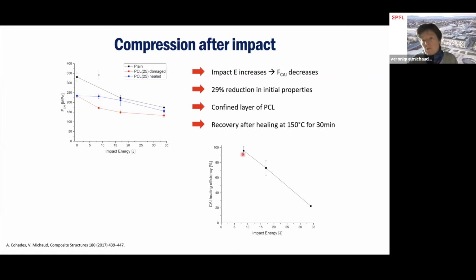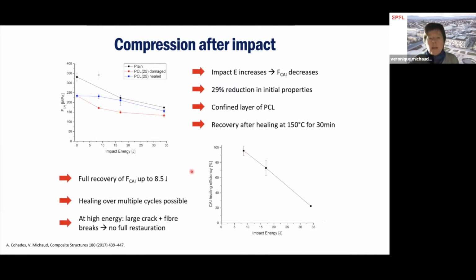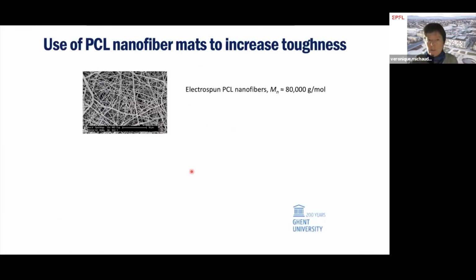And that, of course, the healing efficiency decreases a lot with impact energy because we cannot recover fibers that are broken, but we can recover microcracks fairly well. So healing was also possible over multiple cycles, and at high energy, as mentioned, it didn't work.